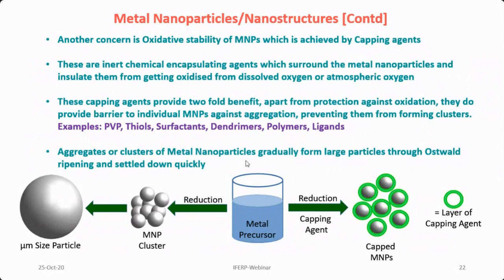Many times people working with iron nanoparticles are actually working with iron oxide nanoparticles, not iron nanoparticles. Because iron in nanoform is not highly stable against oxidation, it gets converted to oxide very quickly. So to prevent that, what should be done? They use a certain type of capping agent, which covers the surface of the nanoparticle in such a way that it practically insulates the surface from getting oxidized. So dissolved oxygen or atmospheric oxygen cannot come into contact with the surface, and it prevents oxidation.